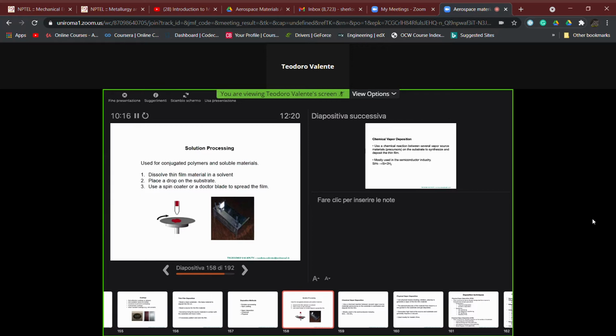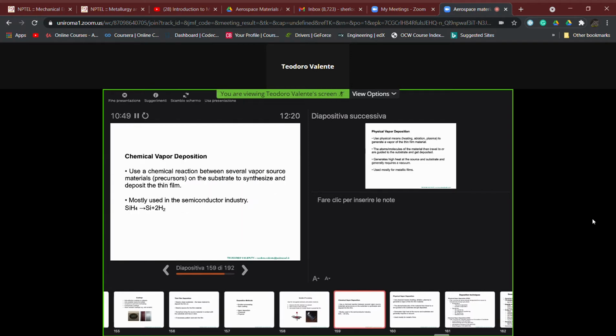A drop, for example, of these materials dissolved in a solvent is placed on the substrate to be coated, and then by rotation we can use a spin coater or a doctor blade to spread the film on the surface, let the solvent evaporate, and thus remaining on the treated surface, by substantially a chemical approach, if we want to say, a solution approach, the final coating fabricated.